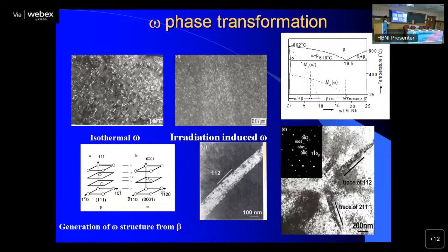So we have to ensure that this does not happen because omega is a brittle phase. So this is the isothermal omega, which you can get during fabrication, and you have to avoid its formation. So that is the information that gets carried on to the shop floor of the fabrication plant from the basic research. The omega phase can also form due to irradiation, and that's not good because again there's a situation where it will make the material brittle. For instance, the pressure tube.